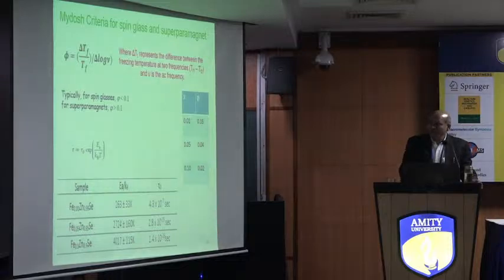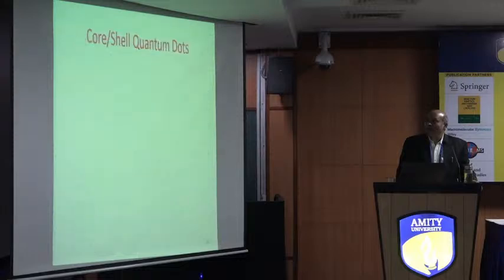We calculate the Mydosh criteria for different concentrations of iron. For 1%, it is showing a superparamagnetic material, but if you go to higher concentrations, 5 and 10%, it is showing some spin glass behavior in the ZnSe quantum dot. So this is the finding here.